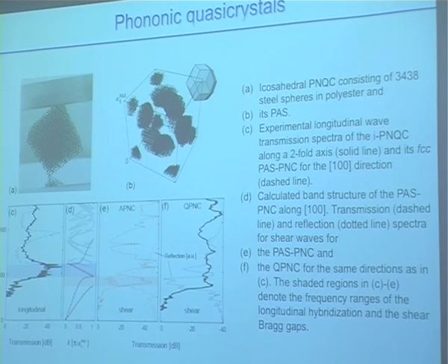And also phononic quasicrystals. So phononic crystals you use for manipulating elastic waves or sound. Yeah? And this is also scale independent. You can manipulate seismic waves with a wavelength of hundreds of meters, or ultrasound waves, or even phonons. Yeah? Phonons, this means for thermal protection, for example. And it works. Here you see, for example, such a phononic crystal made of steel balls in a polymer matrix, 1 millimeter diameter steel balls, yeah? Arranged in a quasi-periodic way, and then you get band gaps which are omnidirectional. And this is what's quite useful for such devices.